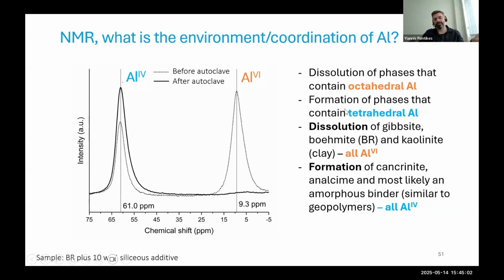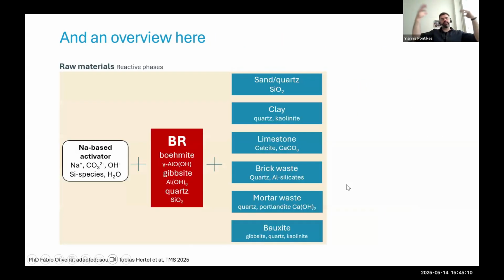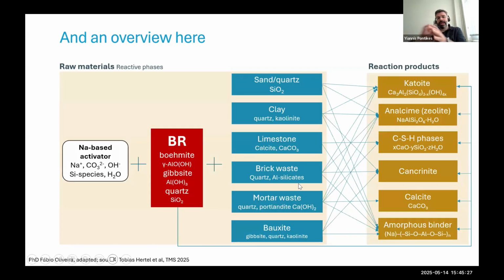So you go from octahedral to tetrahedral, and that confirms the dissolution of certain phases and the formation of your cancrinite and analcime. And then you start thinking, okay, how can I make this now better? So you start exploring different additives. What can you add? It should be low cost because you want to make a brick. So you can say, okay, what if I put clay, quartz, limestone, brick waste or mortar waste and so on? And you have all kinds of different now combinations of reactions.